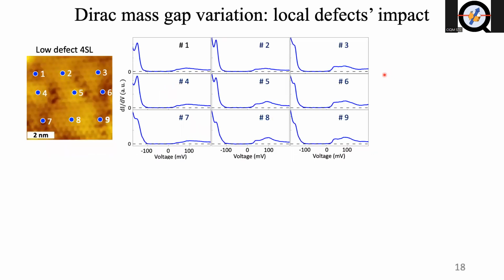So let's take a look at our clean, low defect samples on the first layer, and the data points. The spectra corresponding to the data points are as follows. You can see that although the small features may vary a little bit from point to point, overall the gap size remains very neat and uniform. And most importantly, the Fermi level is actually inside the gap. That means this is an intrinsic sample. So in the low defect sample, the Fermi level lives within the gap, and we see a clean gap with uniform sizes.